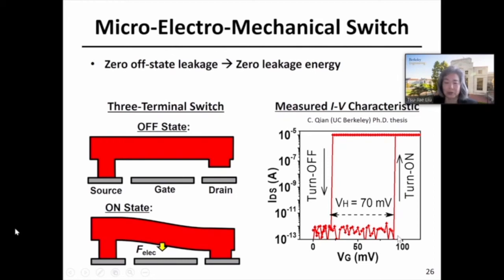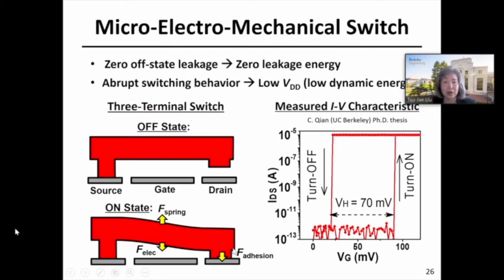And then when you have the switch in the on state, there's some contact adhesive force, right? Van der Waals force that holds those two electrodes in contact. So when you lower the voltage back down to reduce the electrostatic force, the spring restoring force of the deformed structure will cause the beam to actuate out of contact. But there's always some hysteresis because of this contact adhesive force. But we can engineer the contact adhesive force and the stiffness of the beam to make this hysteresis really small, or purposely to cause this switch to stick on, depending on whether you want non-volatile operation or volatile operation like for